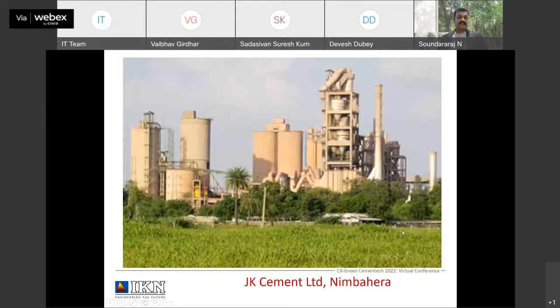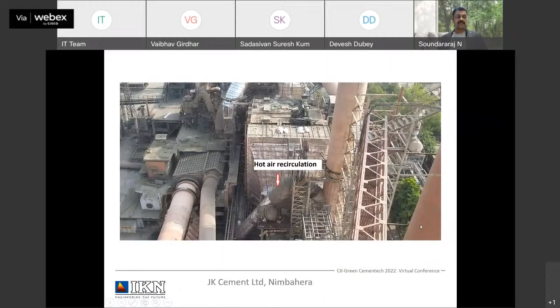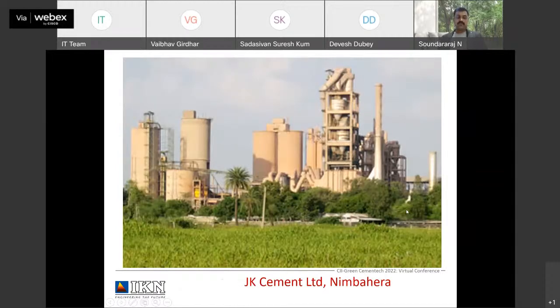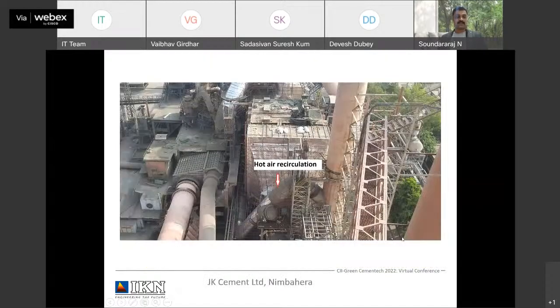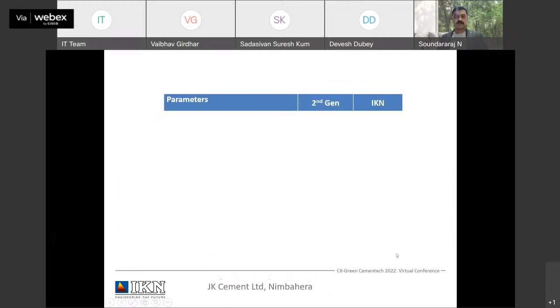In the case study, I'm going to share an interesting fact about the JK Nimbahera Line 3 IKN cooler. They had a conventional cooler with good WHRS generation. They decided to improve the recuperation. To improve the recuperation and reduce the clinker temperature, they wanted a new efficient cooler. When they approached IKN, we gave a solution with hot air recirculation to maintain the WHRS performance without sacrificing fuel consumption. This is the JK Nimbahera cooler, and you can see the hot air duct from the cooler stack at 120 degrees, recirculated to the selective cooling fans in the mid zone. How did the cooler modification with HAR benefit them?